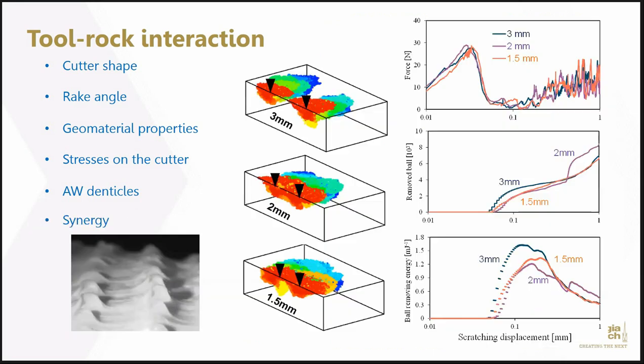We also look at the synergy. If we see all these cutters, all these denticles, they are gapped with a certain distance. We look at, for example, the case where we put two denticles too close to each other, 1.5 millimeters, and they move simultaneously. They will remove the particles along the cutting path. They also over-crush any particles in between. However, if we leave the two denticles separated apart, and the two scratching marks do not interact with each other, then the two will act independently.